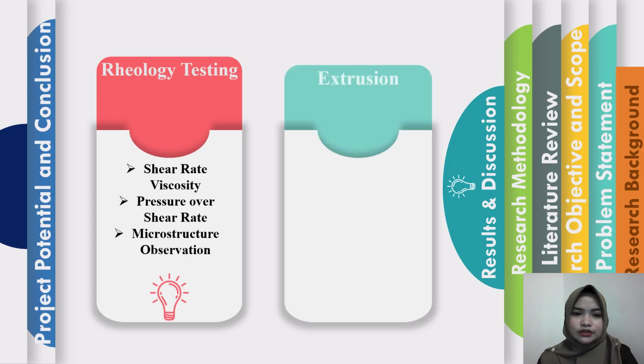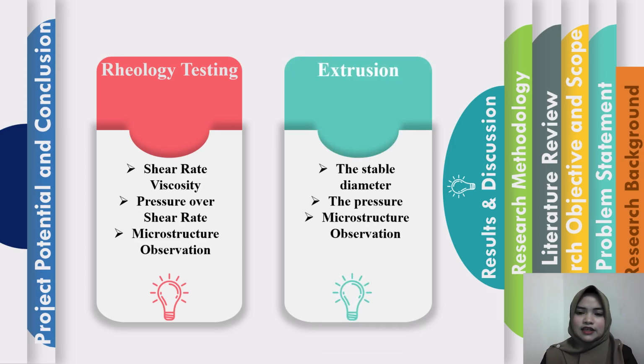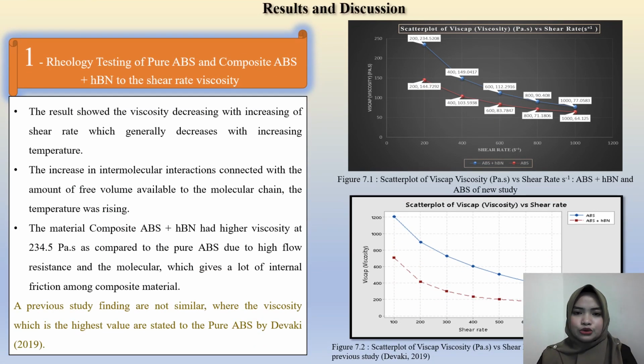Then we proceed to the results and discussion, which consists of two types: rheology testing and also the extrusion. We go first to the rheology testing of pure ABS and composite ABS HBN for shear rate versus viscosity. The results show the viscosity decreasing with increasing shear rate, which generally decreases with increasing temperature. The increase in intermolecular interactions is connected with the amount of free volume available to the molecular chain.